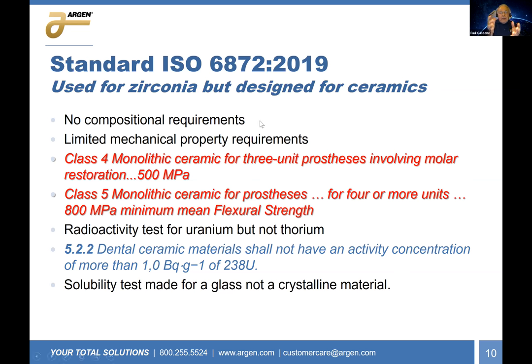So the manufacturer does not have to provide to you, the dentist, or to the laboratory, what is actually in the zirconia. They have limited mechanical property requirements because, again, the source was the original aluminous porcelains, which had very low strength. So they couldn't eliminate the material if they wanted a higher strength. So as a result, for a class four, a 3-unit bridge, it has to have a flexural strength of only 500 megapascals. And all of our zirconias that we recommend for 3 units or more have greater than 500 megapascals. We just can't tolerate that low a stress level. And the same thing for class five.